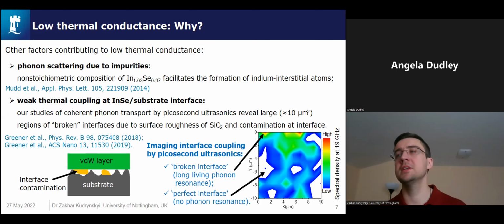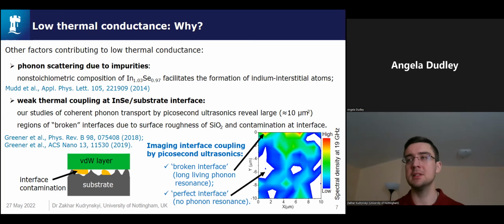The two interfaces interact elastically via van der Waals and Coulomb forces, and due to strong dependence of the potential energy on distance, the increase in the separation between the layer and its supporting substrate caused by an imperfect interface, ionized defects, and large electron-phonon interaction in indium selenide can change the ability of phonons to be transmitted across the interface.